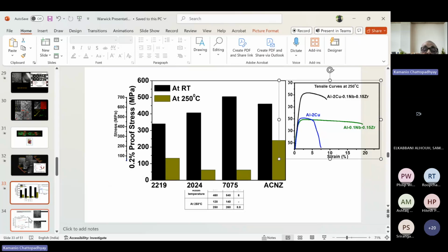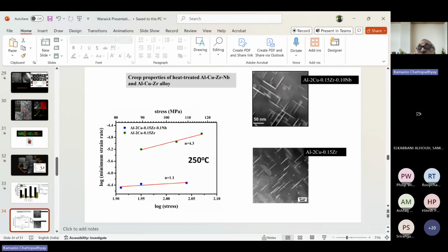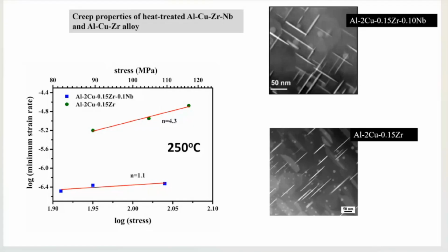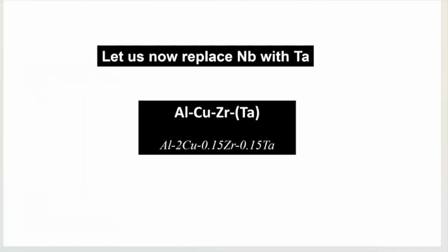We also looked at creep strength at 250 degrees centigrade. And when you look at the creep strength of these alloys, they're pretty good. Aluminum copper zirconium itself is good, but for aluminum copper niobium zirconium, the minimum strain rate at 250 centigrade, as a function of stress, is quite low, and therefore it is quite attractive as an alloy development. Let us now replace niobium with tantalum.